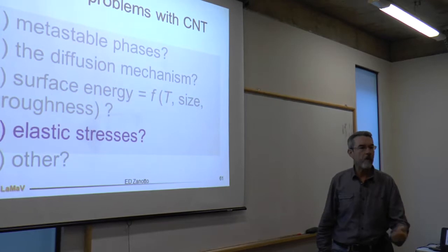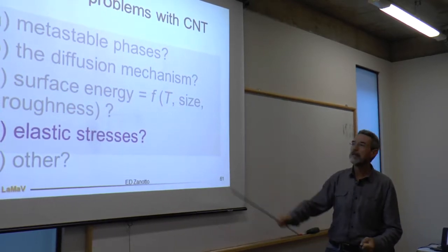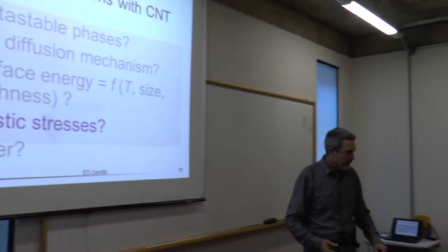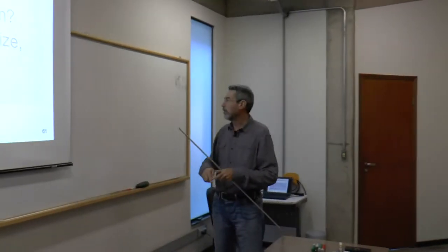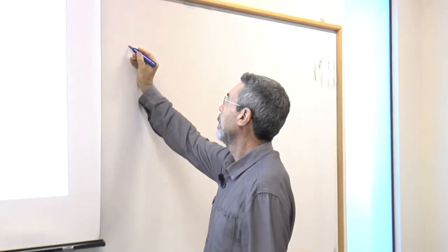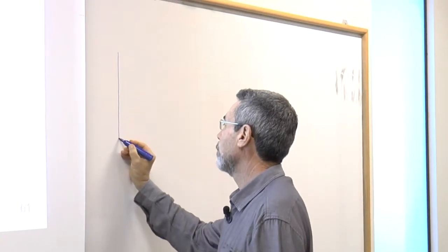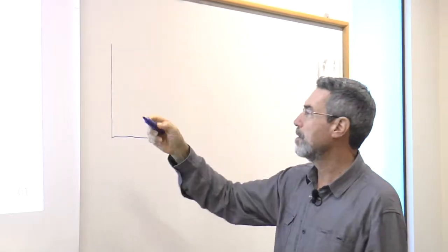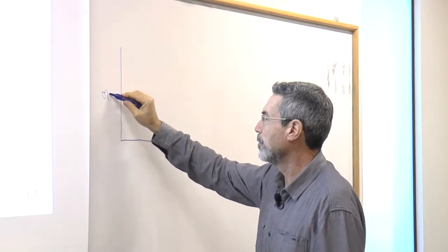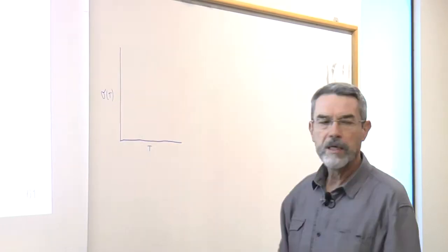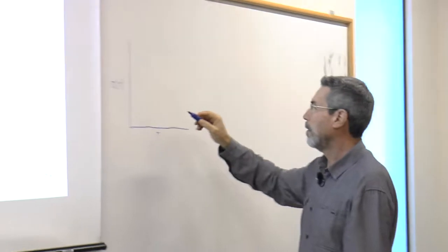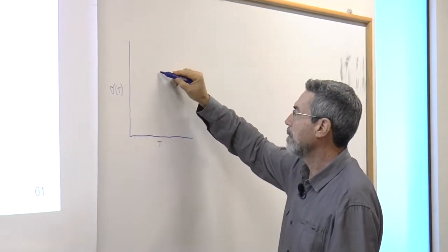Of course, we can force fit a temperature-dependent surface energy. In that case, the result, and I believe I have shown this in the previous lecture, but let's recap a little bit. If we force fit, what's the value of the surface energy? The value of the surface energy to bring theory and experiment into agreement, we find out that if this is the maximum,